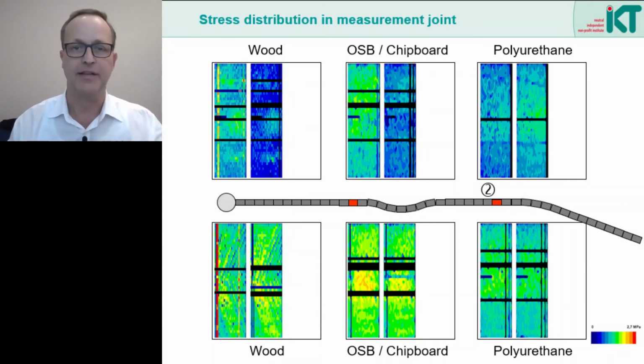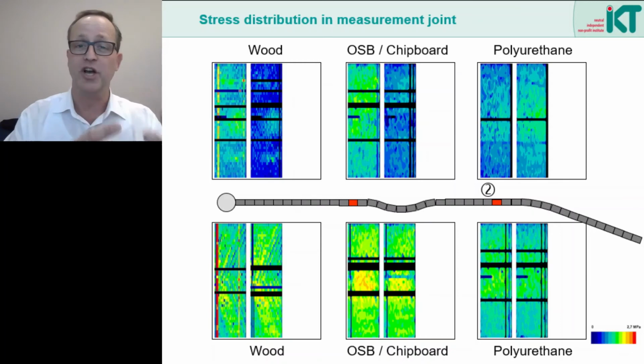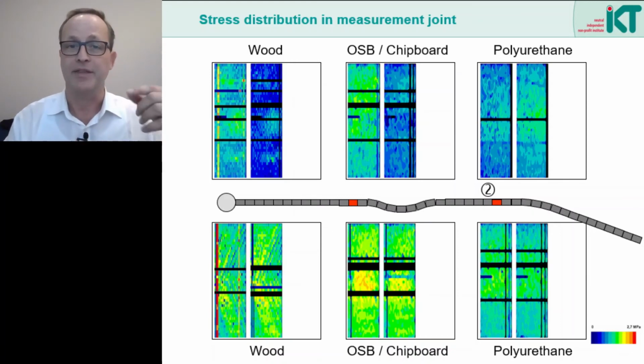With the plastic, the polyurethane, the measured values haven't changed at all. This material obviously behaved purely elastically in the curve and it must have returned to its original shape. With solid wood and chipboard, however, the situation is different. In the section where the inner side of the curve has been, the stresses are now significantly lower. Obviously, the wood has been strongly compressed and has undergone plastic deformation.